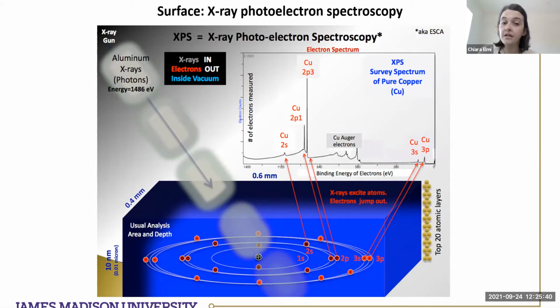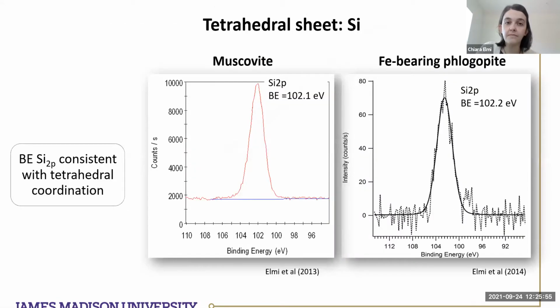That's a lot of information at the surface, because we know what is the surrounding around the specific cations in the structure. And based on that, we can know if there's any reconstruction or relaxation. Here the result. So we look at each element in the site, and we notice that the silicon has a binding energy that is consistent with the tetrahedral coordination. And that is based on the energy that is used for calculating the jump of the electrons in the 2p orbital of silicon. Same for the phlogopite. So most samples maintain this coordination in the T layer.